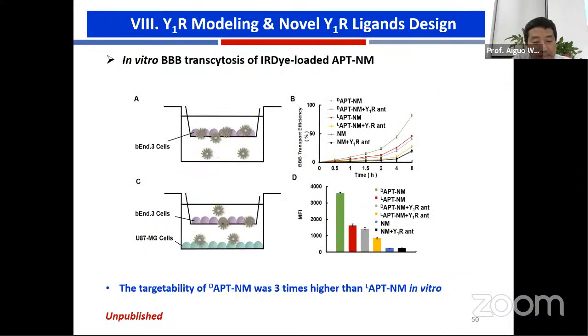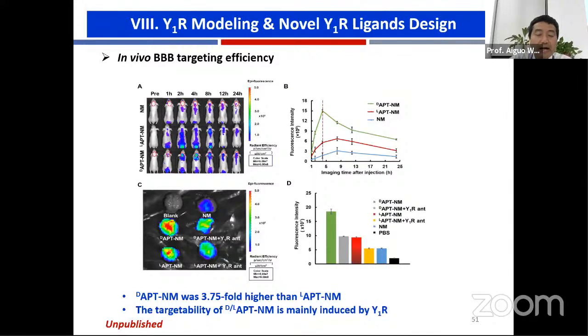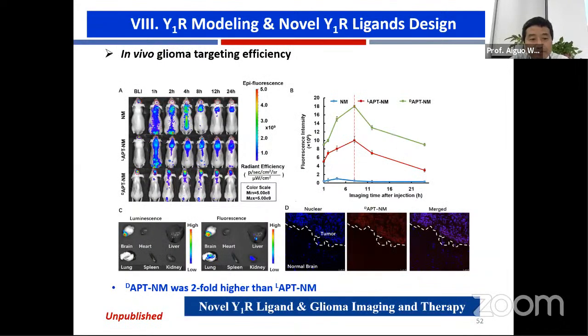Further, we found the nanosystem with the targetability of the D-type APT nanoparticles was 3 times higher than the L-APT nanomaterials in vitro. And further, in the animal model we found the D-type APT nanoparticles was 3.75-fold higher than the L-APT nanomaterials. And also, the targetability of the D- and L-APT nanoparticles is mainly induced by the Y1 receptor. In further work, we found the D-type APT nanomaterials was 2-fold higher than the L-APT nanomaterials.